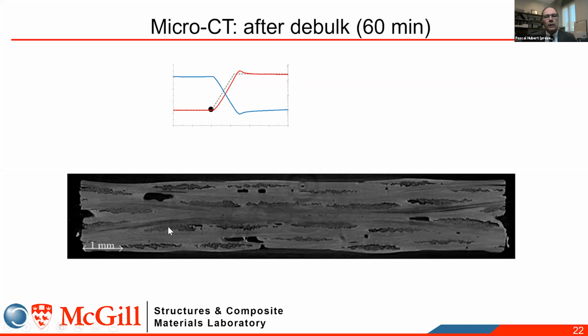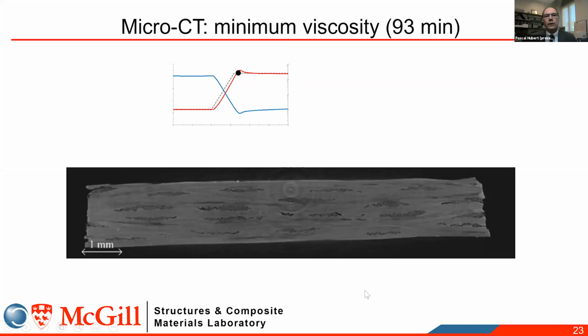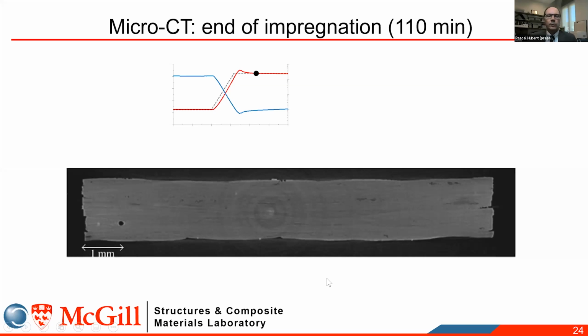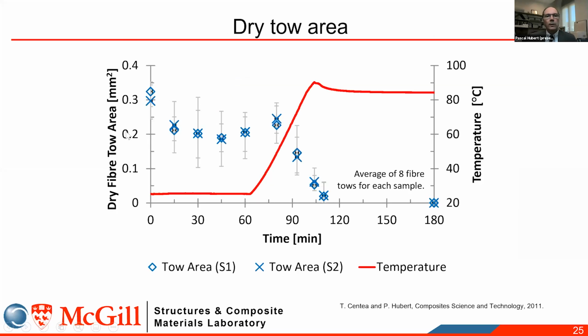But obviously, there are still a lot of unimpregnated toes. As we increase the temperature and therefore decrease viscosity, now the resin can start to flow inside the toe. And we see that there are still some dry toes, but the area is shrinking a little bit. And at the end, when we get the full impregnation, we can see that the resin has infiltrated the toes. And now you can take these images and do some quantitative analysis of the dry toe area evolution with time. And that's what I'm showing here.